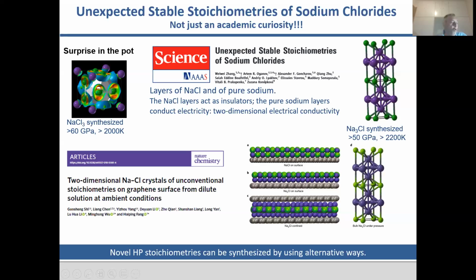Because two years ago, a different group using conventional chemical approaches managed to synthesize these compounds at ambient conditions, and they discussed exactly this two-dimensional conductivity. And you may see here how they compare what they managed to synthesize on top of graphene surfaces with what we found under pressure. So the reason that I'm discussing this is to make the point that with pressure, it's not only that we can access novel stoichiometries and just stay there. I think high pressure has the advantage that it is the optimum way to run ahead, to probe, to find new stoichiometries, and sometimes the field might come back using conventional techniques and synthesize this kind of compounds.